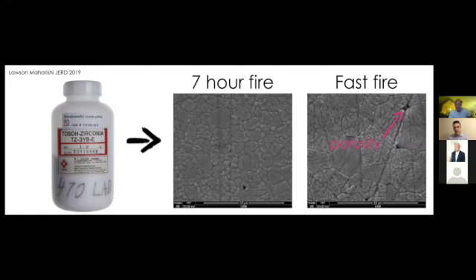But if you took a material that wasn't meant to be speed fired, so we took some materials that weren't speed fire materials, and then we put them in the speed fire, it really screwed them up. They got this humongous grain growth, and even worse, they had all these porosities. So they were really opaque and much weaker.